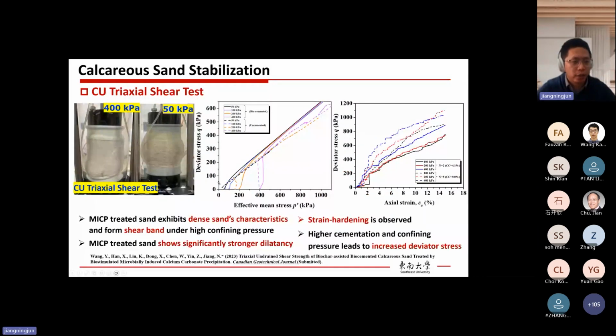For the CU test, the first graph also shows the failure state of the samples at 50 and 400 kPa confining pressure levels. Then the second graph shows the deviator stress versus effective mean stress. Because it's a CU test, we can see the change in deviator stress in this way. The dotted line shows the uncemented samples, and the solid line shows the bio-cemented samples. Obviously, compared with uncemented samples, the lines for bio-cemented samples shift to the right. So it means it becomes more like a dense sand.